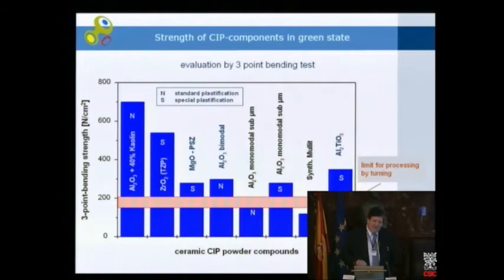And I will just show you this in one case. A 3-point bending test, very primitive in this type of testing. But let's look at the figures, what we can achieve as the so-called strength of CIP components in green state. And the limit for processing by a modern turning operation is in the range of just 2 megapascals, so that's not much.